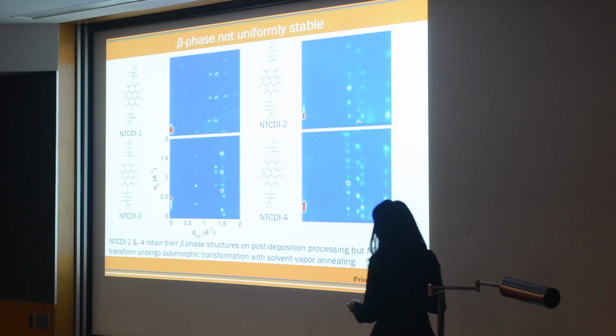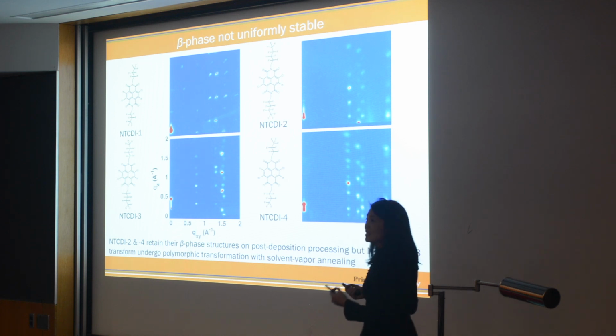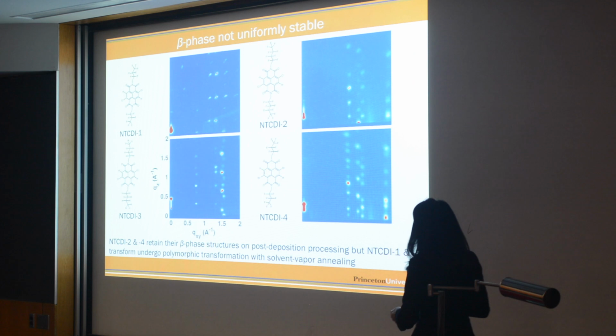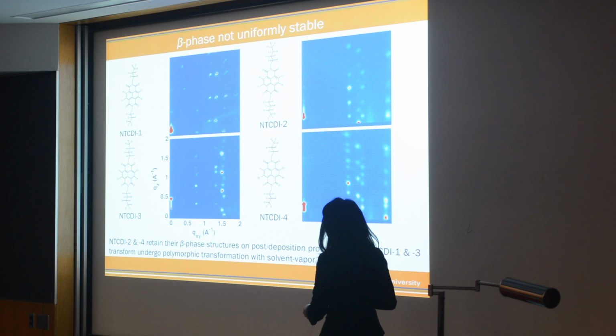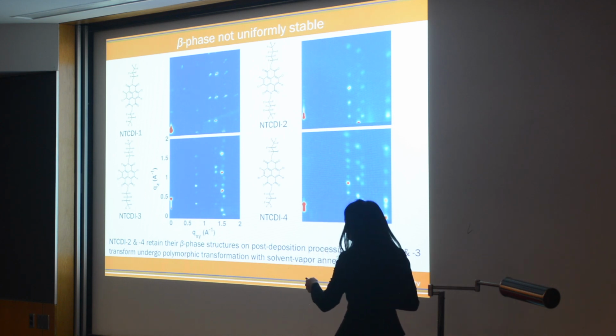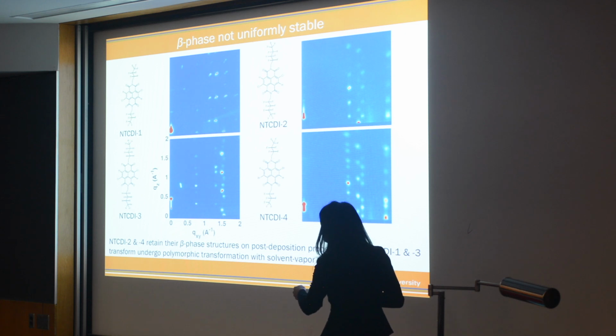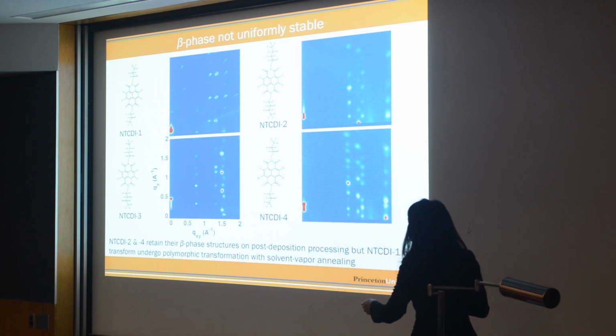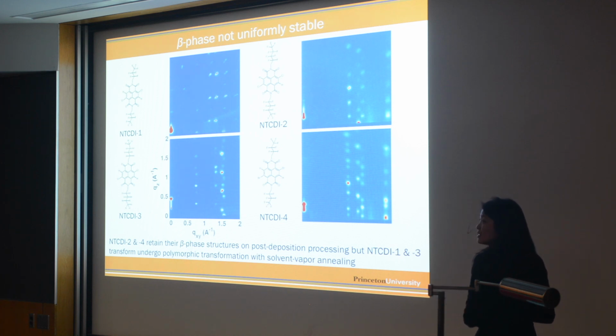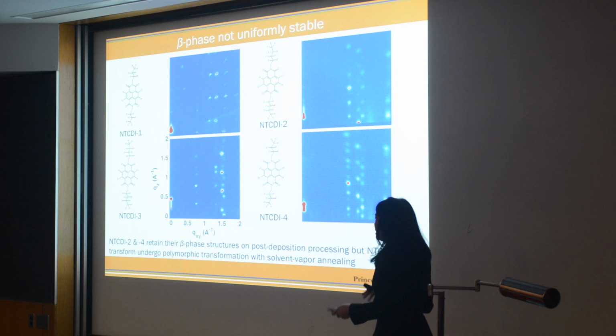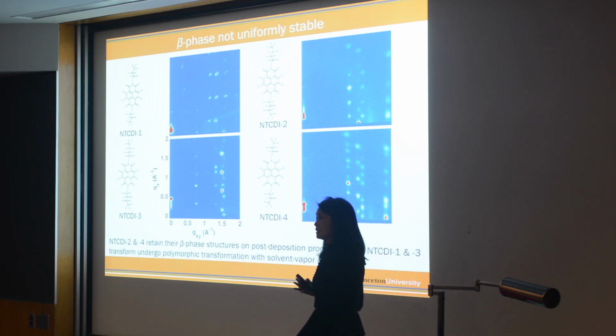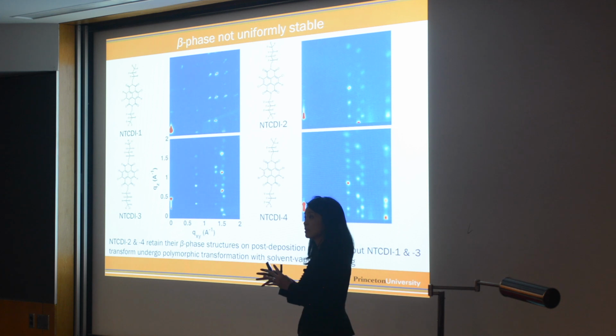So what you'll notice is these are X-ray diffraction patterns, and they're again crystalline. But if you have a keen eye, you'll notice subtle differences. In the beta phase, the in-plane reflections only start at about 1 inverse angstrom. Once we solvent vapor anneal NTCDI1 and NTCDI3, we begin to see reflections at lower Q. And in fact, the out-of-plane reflections actually shift to higher Q. Okay? So it turns out if you index the NTCDI4 and NTCDI2, they retain their beta phase structure. But in NTCDI1 and 3, when you solvent vapor anneal it, we now convert from the beta structure to the alpha phase structure.